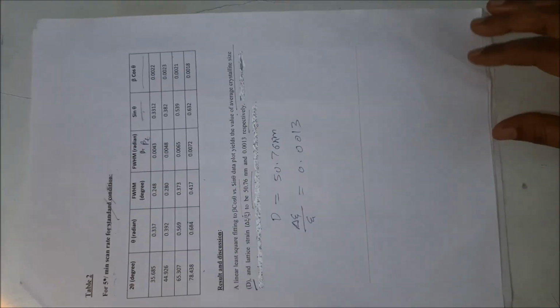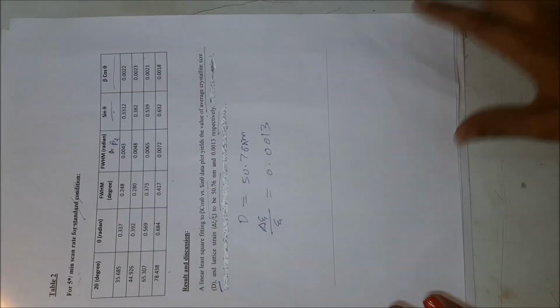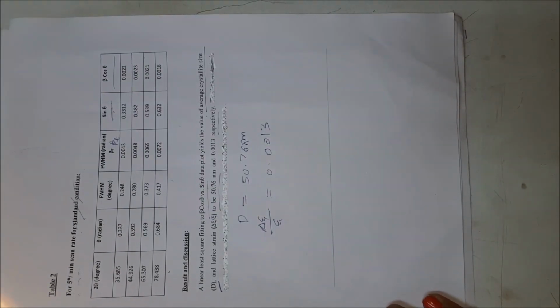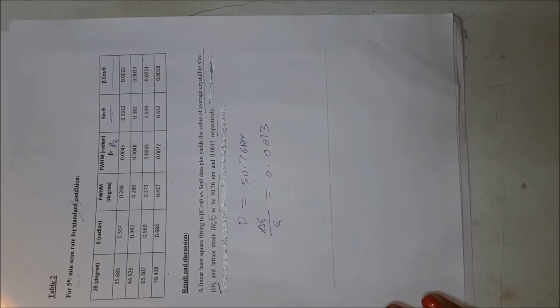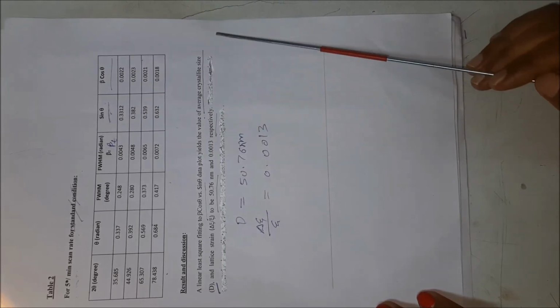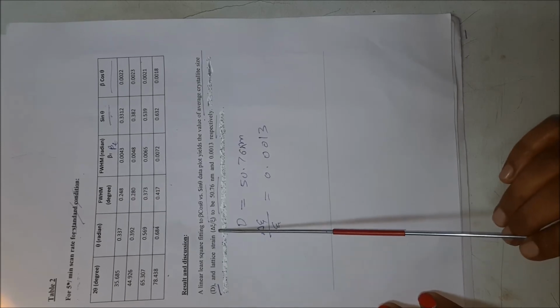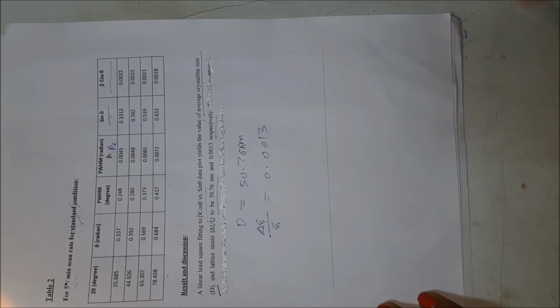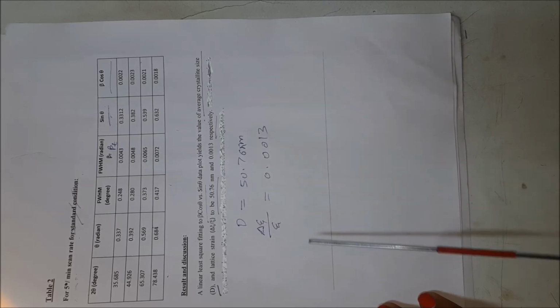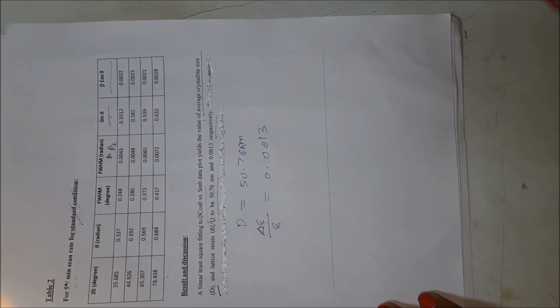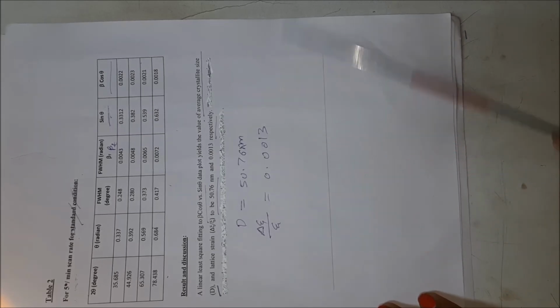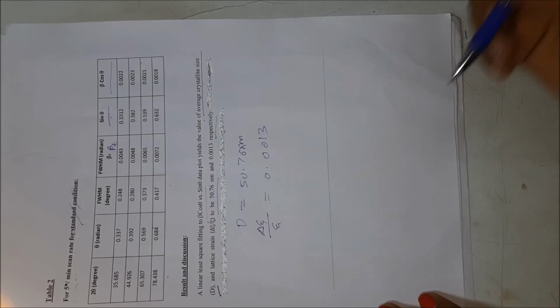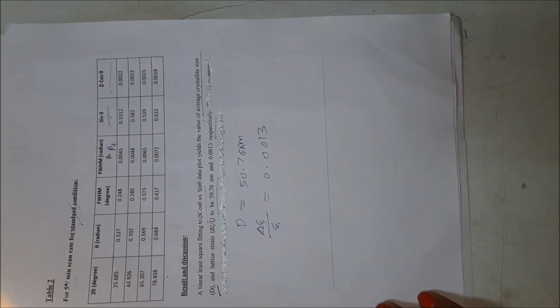Finally, we can say that a linear least square fitting to the beta cos theta versus sin theta data plot yields the value of the average crystallite size d and the lattice strain delta d upon d to be 50.76 nanometer and 0.0013 respectively. It is very clear: the value of d is 50.76 nanometer and delta d upon d is 0.0013. It is a dimensionless quantity because it is the ratio of two lengths. So I hope you liked it. Thank you for watching the video.